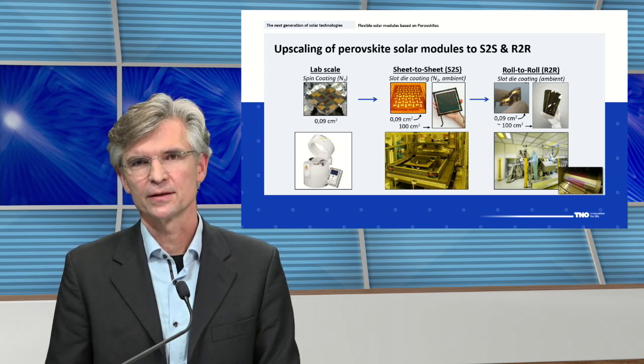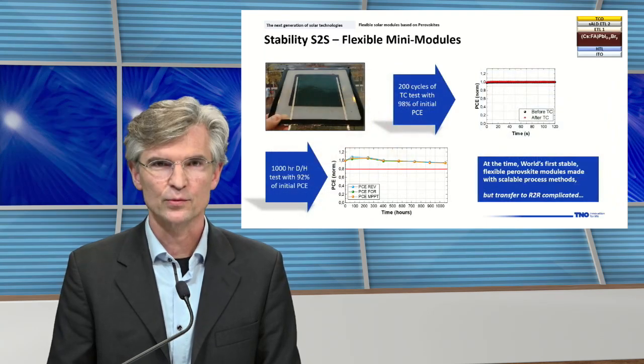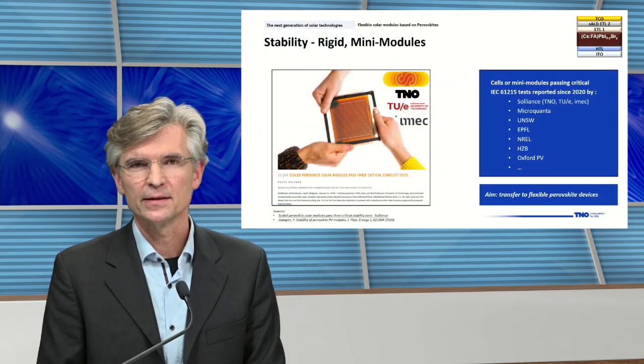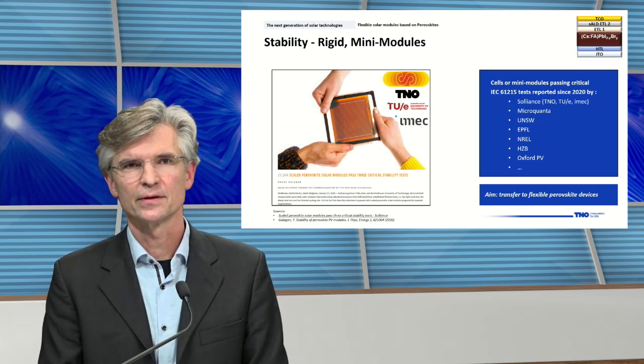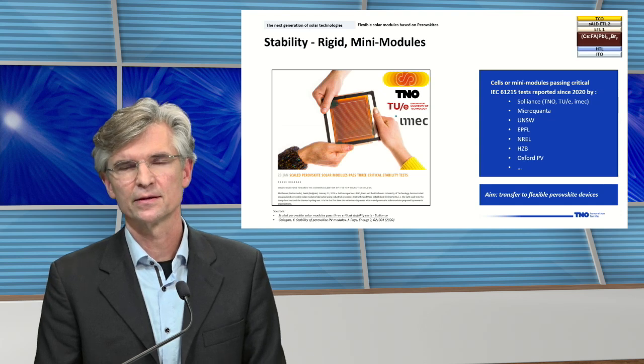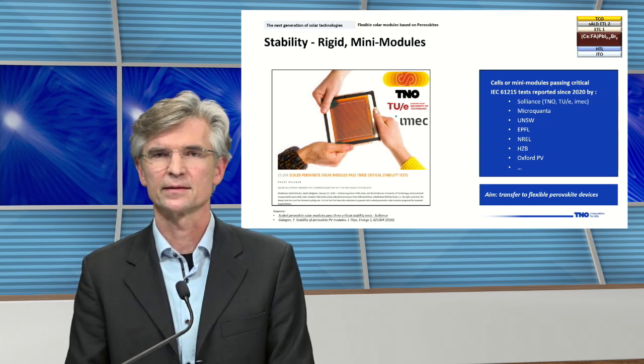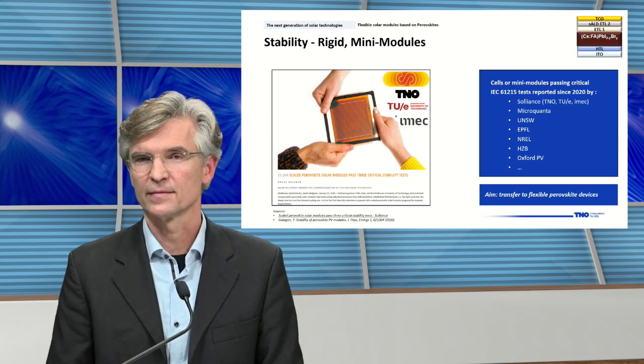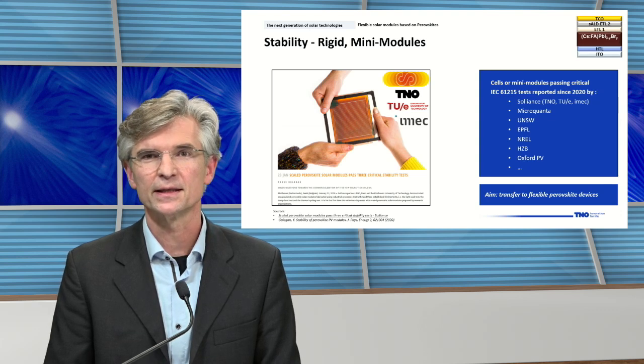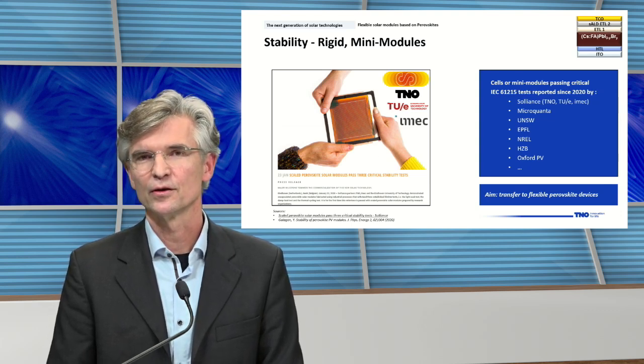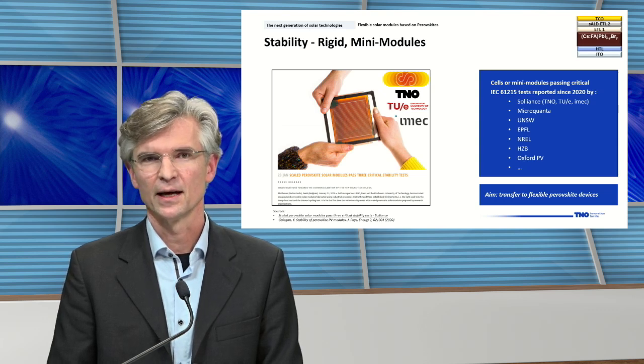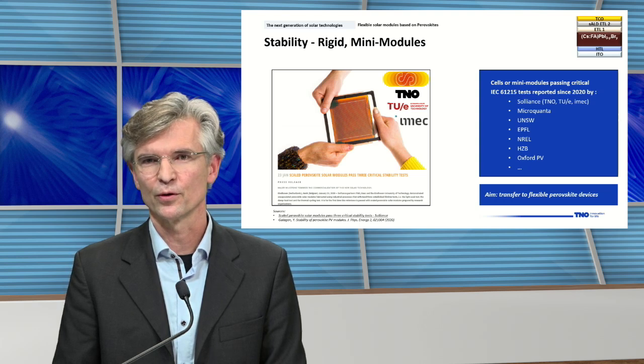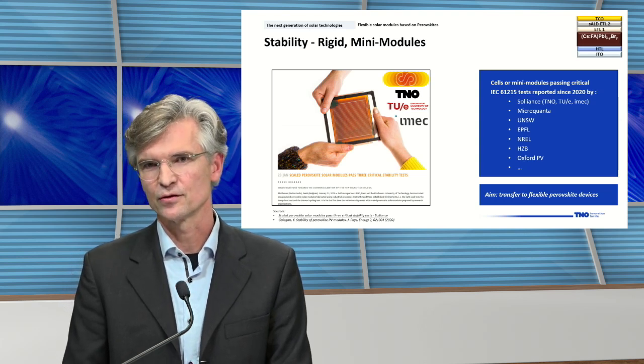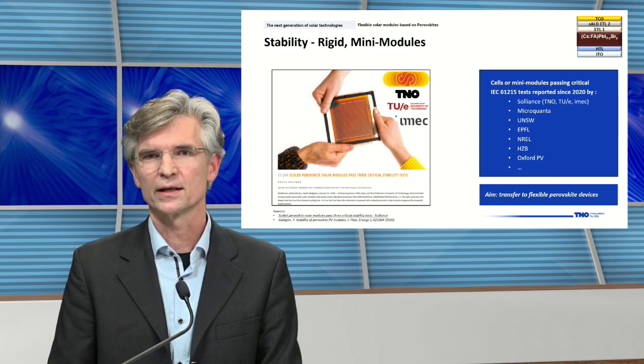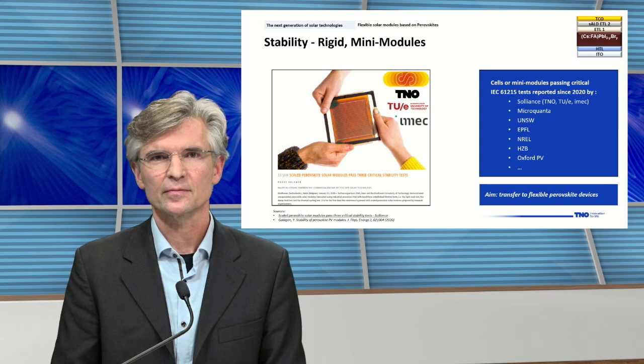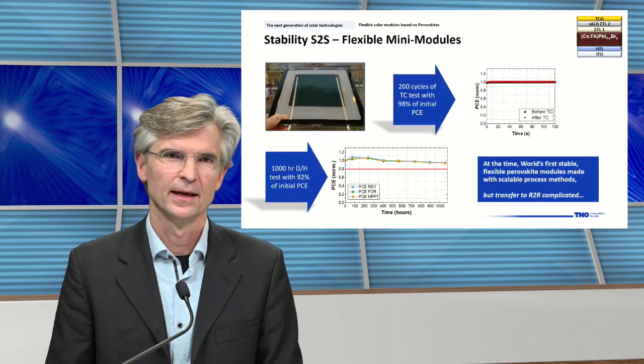Now, a few words about stability. So about stability, in 2020, we achieved rigid mini modules which passed, let's say, 3 critical stress tests. And after achieving this nice result, we published a press release. And since we see that other groups are also achieving similar results, which is, I think, a fantastic achievement for the whole community. And our ambition is then to move this device stack towards flexible substrates. So that is shown on the next slide.